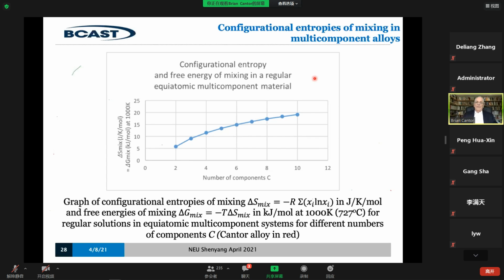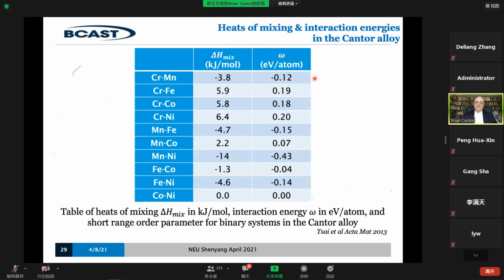And these are the enthalpies of mixing for the Cantor alloys. Now the Cantor alloy, the individual binary enthalpies of mixing are given here, and you'll see that they're not very high. The highest one is manganese nickel, which is 14. So that is just okay to allow the entropy to dominate and for the material to be a random solid solution.